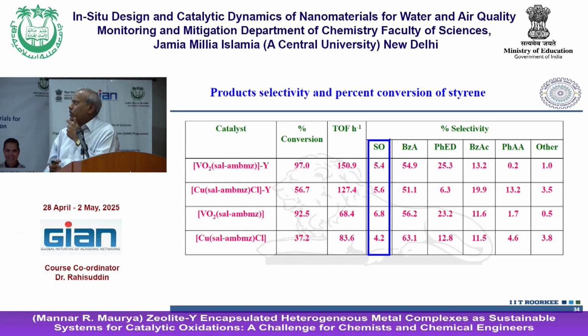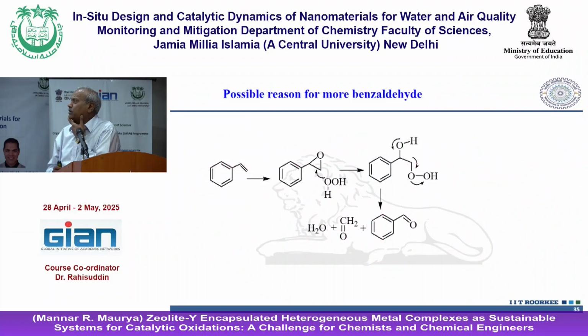So why is it going to benzaldehyde? This is one of the reasons we gave during that period: styrene is going to epoxide, but since you have an excess of hydrogen peroxide, it is further reacting, opening that ring, which is known to open the ring, and then breaking it down, giving benzaldehyde in the maximum yield.